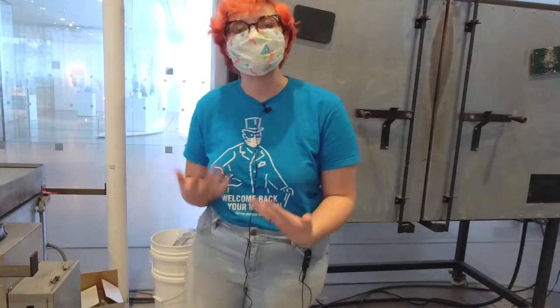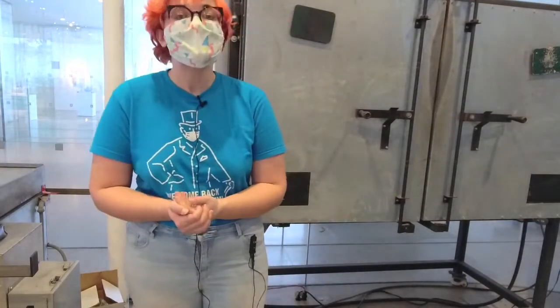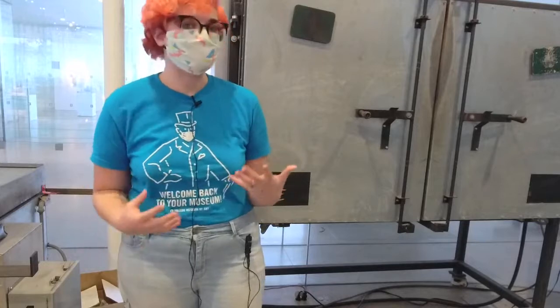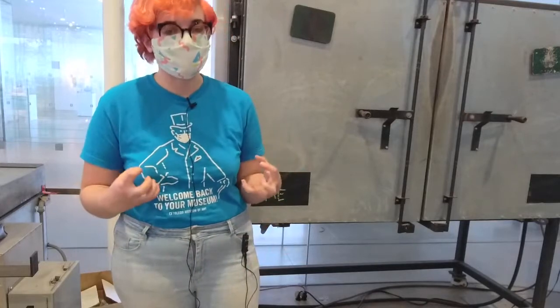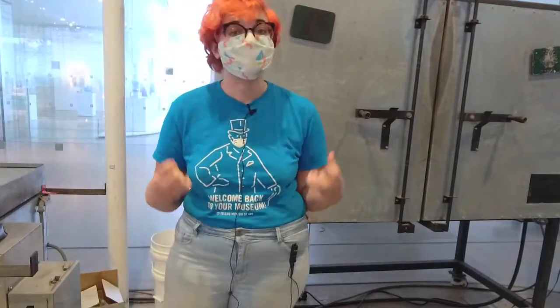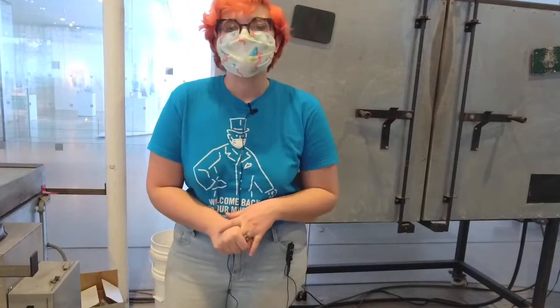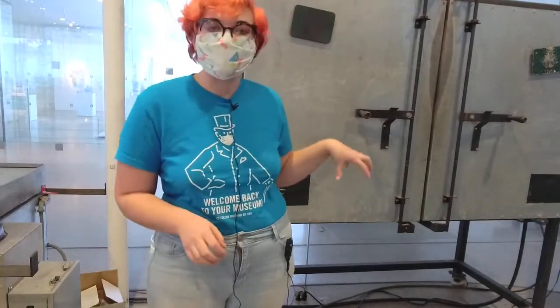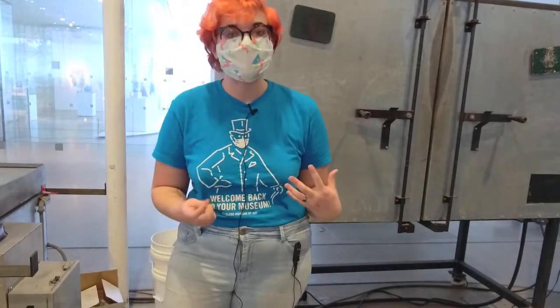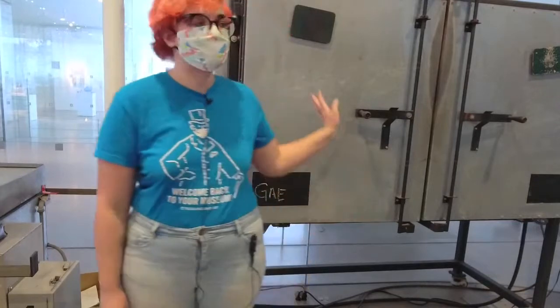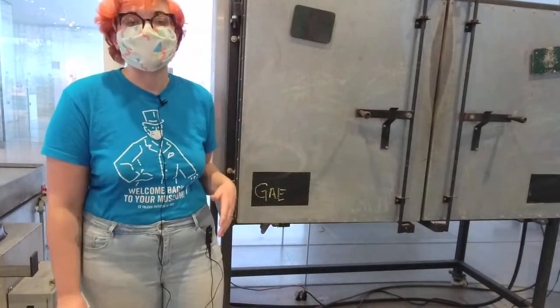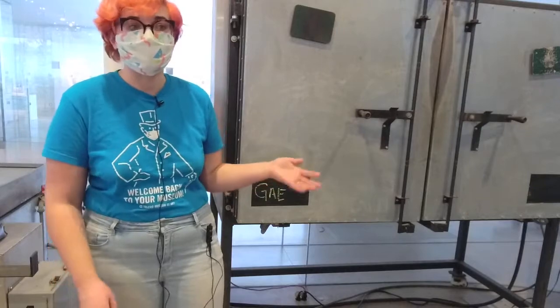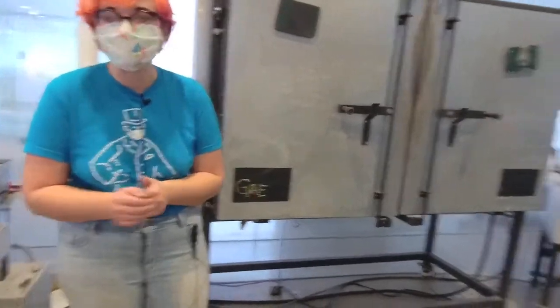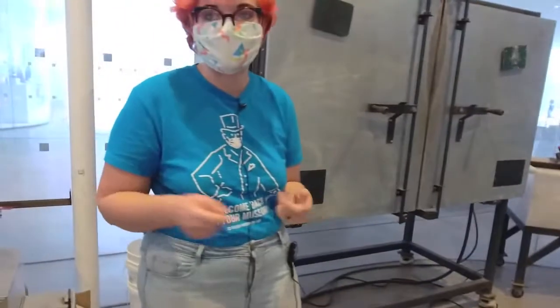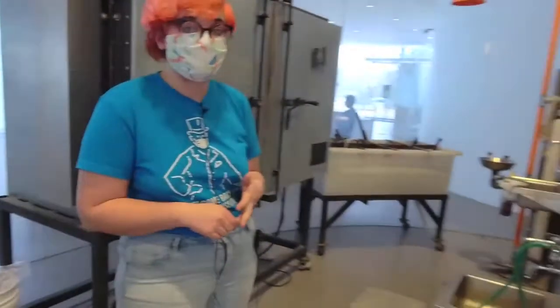The reason that it takes about 12 to 24 hours is because the glass, if it cools down too fast, gets really stressed out and will actually fracture and break apart. So it cools down, relieves the stress, and then once it's at room temperature, we can just take it right out of here and put it into one of our cafe galleries, where it will be for purchase.